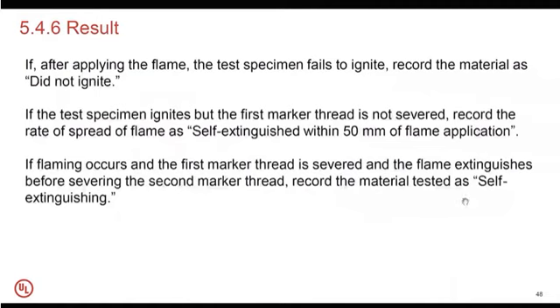So if after applying the flame, the specimen fails to ignite, then it means that this material did not ignite. If the test specimen ignites, but the first marker thread is not severed, then it means that the specimen self-extinguished within 50 millimeters of flame application. If flame occurs and the first marker thread is severed and the flame extinguishes before severing the second marker thread, then it should be indicated that the sample self-extinguished.